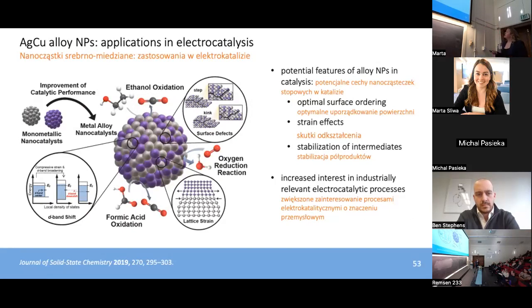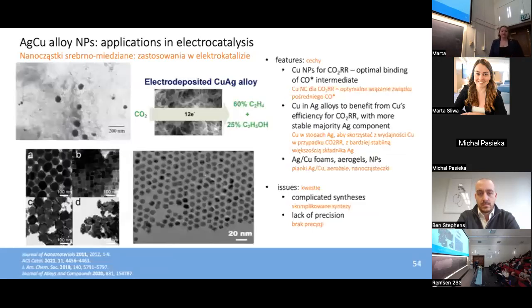Increased interest in industrially relevant electrocatalytic processes has driven efforts to make precise metallic alloy nanoparticles for these types of applications. One of those industrially relevant processes is the CO2 reduction reaction, as Tom mentioned at the beginning of my talk. It turns out copper nanoparticles are great catalysts for the CO2 reduction reaction because of the optimal binding of the CO intermediate in this process to their surface. However, copper is prone to oxidation. We know what happens with the Statue of Liberty, it used to be copper, and this hinders its catalytic efficiency.